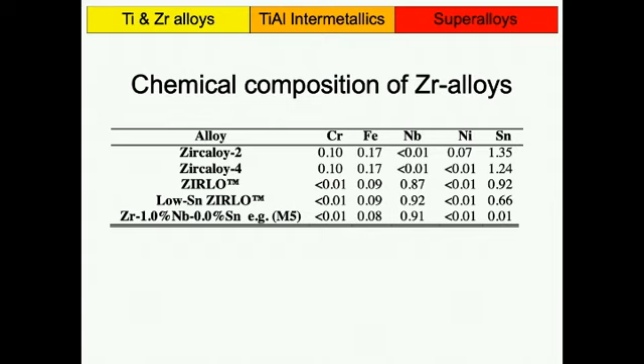Here you have another list of typical chemical compositions. So here the two zirc alloys I've already mentioned. So you can see mainly the difference between the two is in terms of nickel. Zirlo, now you have a niobium addition here. And then you can see the low tin Zirlo. That's what I mentioned earlier, where they actually drive down the tin content from close to 1% to around 0.7%. And in fact, there are new alloys Westinghouse is working on now, which have 0.3% tin, and they have better corrosion properties.